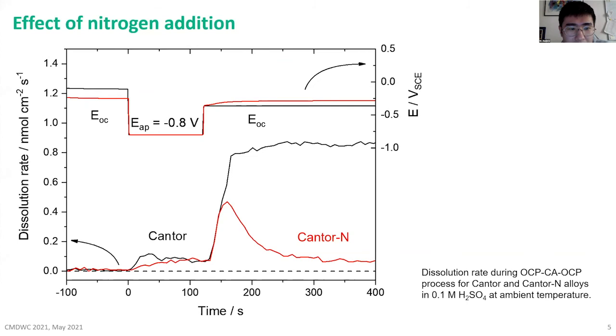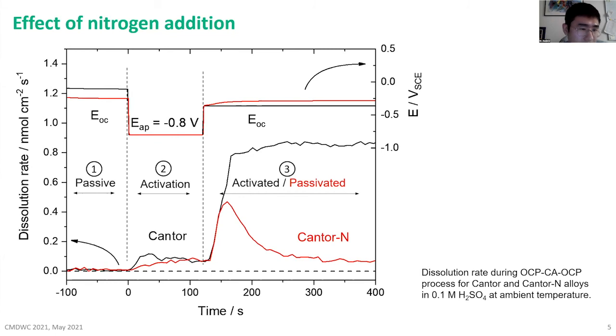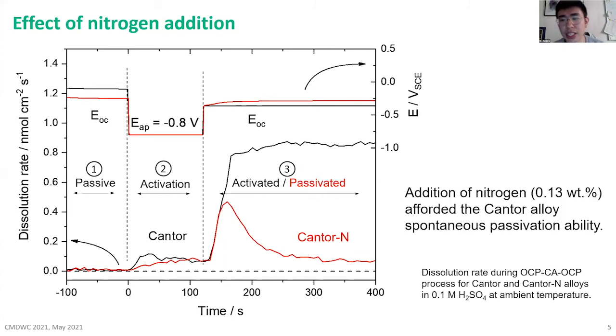Further insights into this: this slide compares the dissolution behavior during the experiment for these two alloys. We can see a clear difference between these two alloys with and without nitrogen. We can also tell this behavior from the open circuit potential, because in the passive state, the open circuit potential for the Cantor alloy was higher than Cantor N. But after the passive film breakdown, the open circuit potential of the Cantor N alloy increased and was higher than the Cantor alloy. And it also corresponds well with the dissolution profile. So we conclude that addition of nitrogen, 0.13 weight%, afforded the Cantor alloy spontaneous passivation ability.